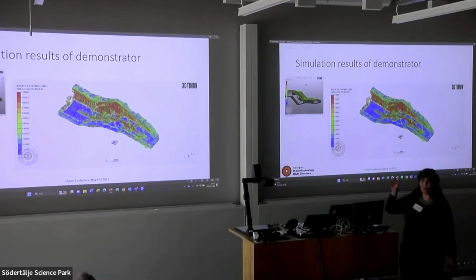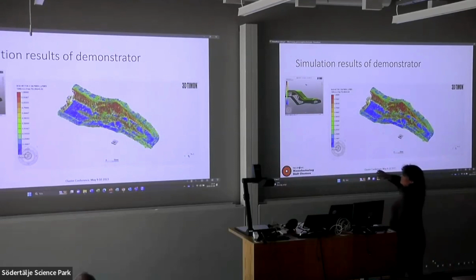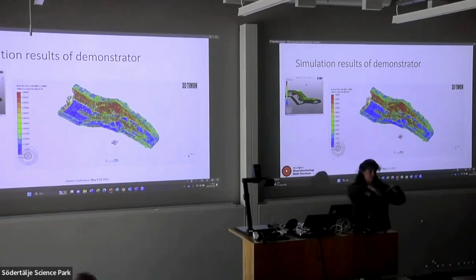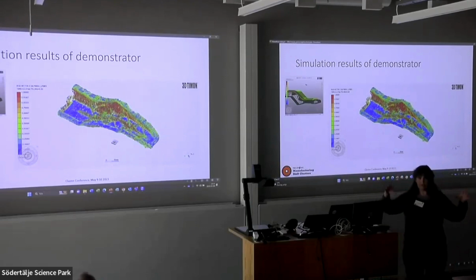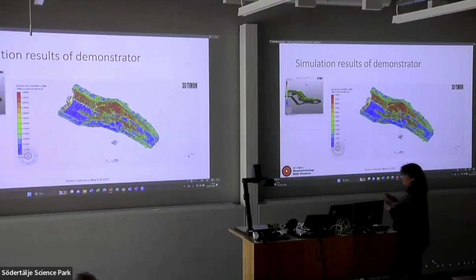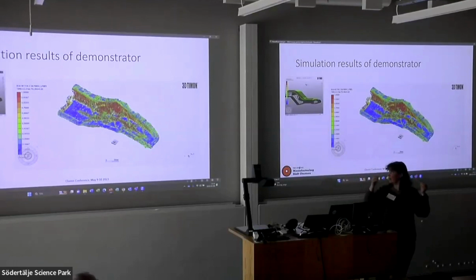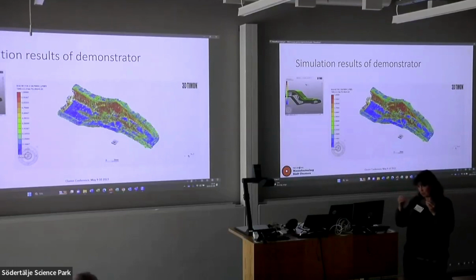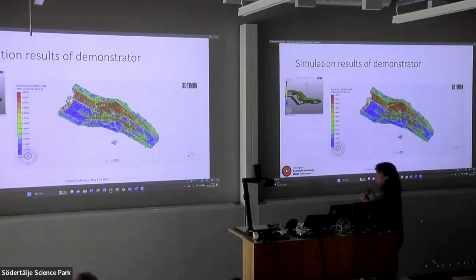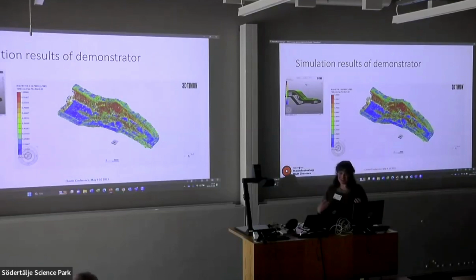3D Timon, as opposed to Moldex3D, has a direct fiber simulation. So they do the flowing of the liquid underneath, and then they superimpose the behavior of the fibers on top of that. They're modeling the fibers as links, though they're not modeling fiber interaction. We're talking about 35% fiber content, so you can imagine there is actually quite a lot of fiber interaction, but the standard approaches at the moment don't include it. So we try and get around that by modeling it in the homogenized fluid models.